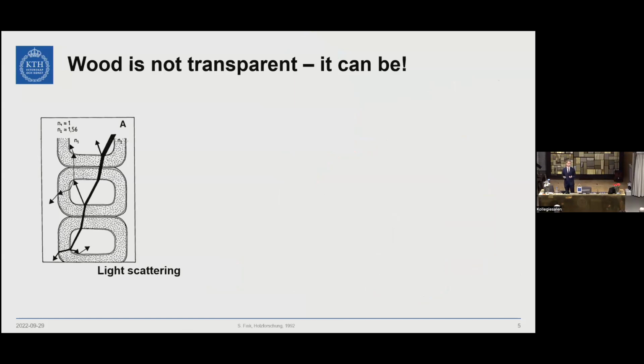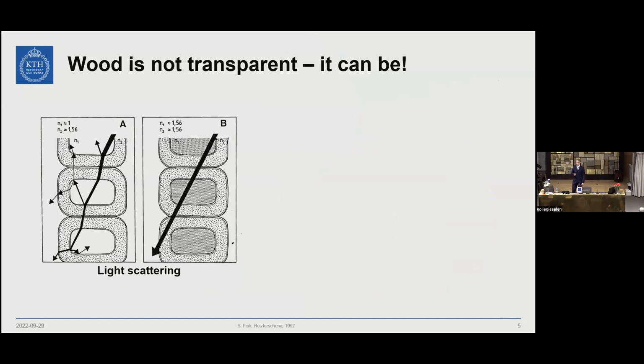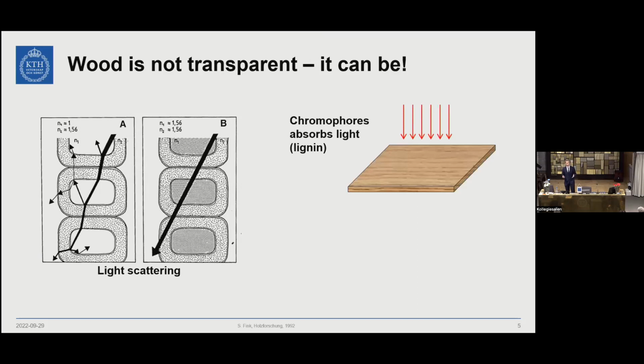One of the reasons why wood is not transparent is because of light scattering effects. Wood is quite a porous material. Some species could have up to 95% porosity inside. So in theory, we can make it transparent if we fill these pore volumes with a matrix or any material that matches the refractive index and is itself transparent. In practice, of course, it may not work just by filling it.